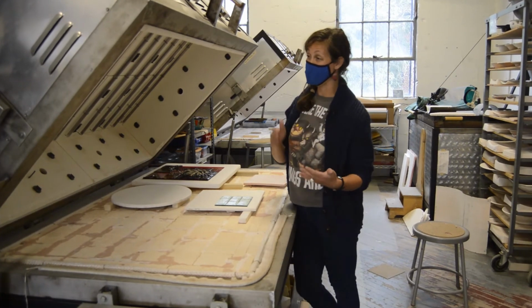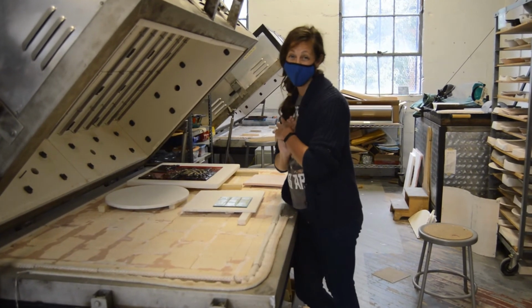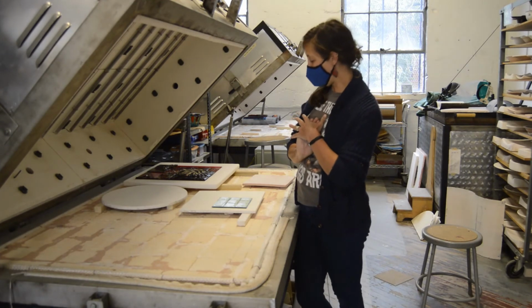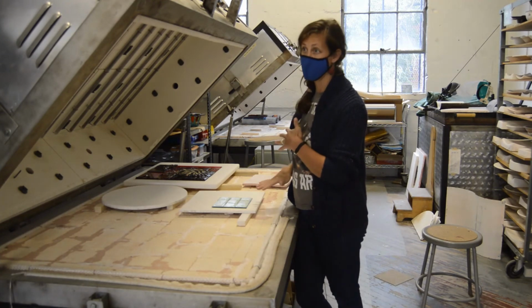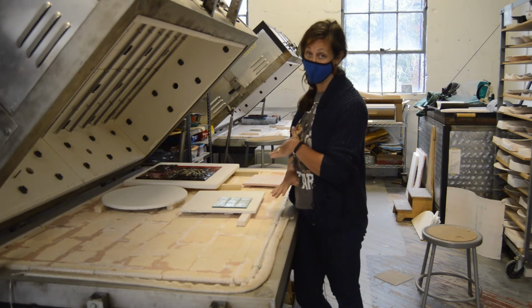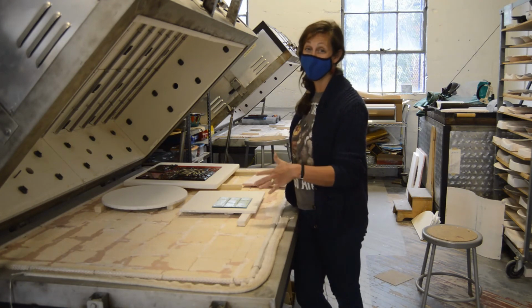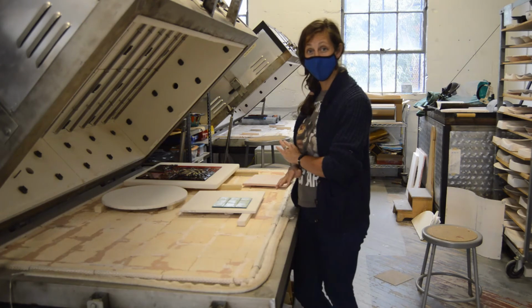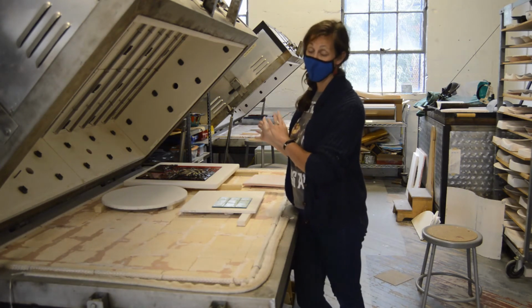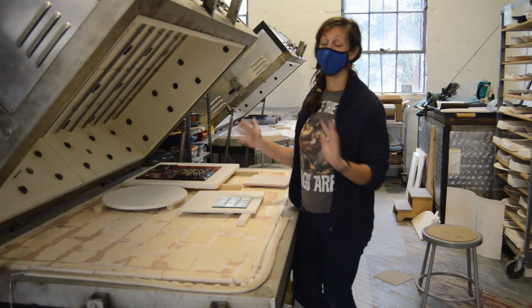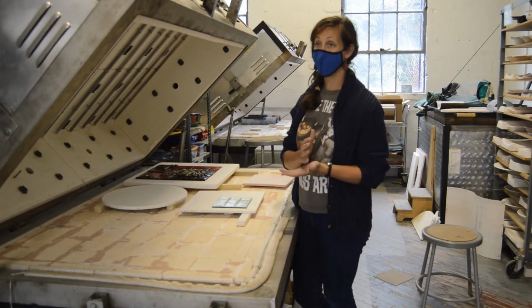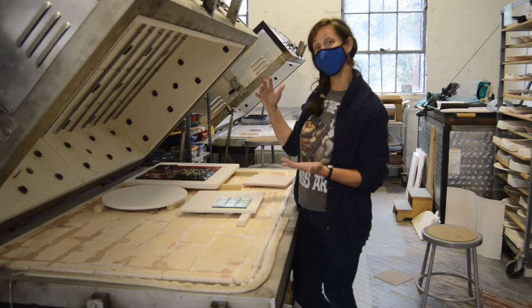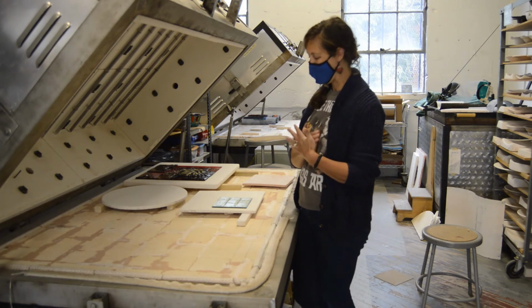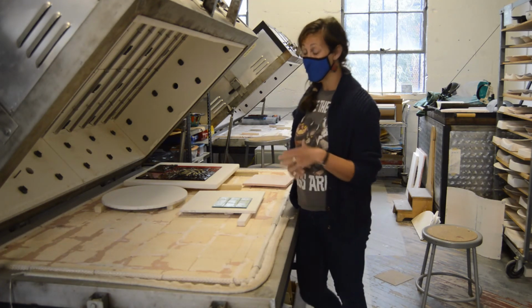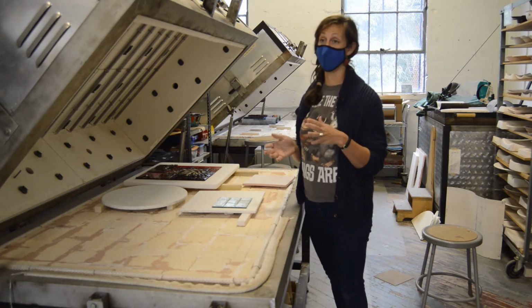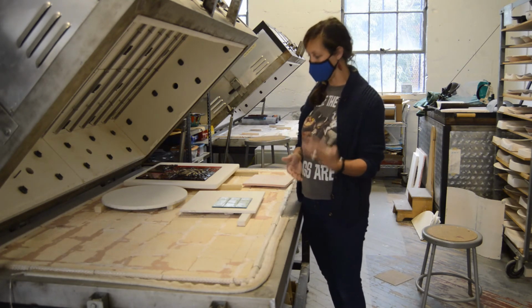It takes about 12 hours for this kiln to get up to temperature, and our forming temperature for our full fused dish is going to be around 1450 degrees. But then this glass only has to sit there for like 5 to 10 minutes, and it'll take the remaining 12 hours to slowly cool back down to room temperature. So all the time is really in slowly heating and slowly cooling the glass. Similar to glass blowing, once the glass is at temperature, it can move and change really quite quickly.